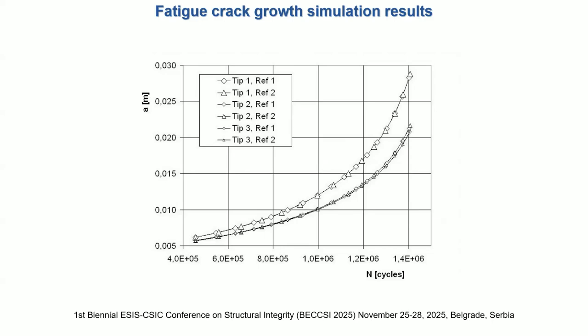This is what I wanted to show you: this analytical method for taking into account interaction of multiple propagating crack tips. We can do more examples. Some cracks can be longer and others shorter, and again to see this interaction. So basically, there is no interaction if these cracks are far apart and if they are short. But if they are big, then there is very strong interaction.